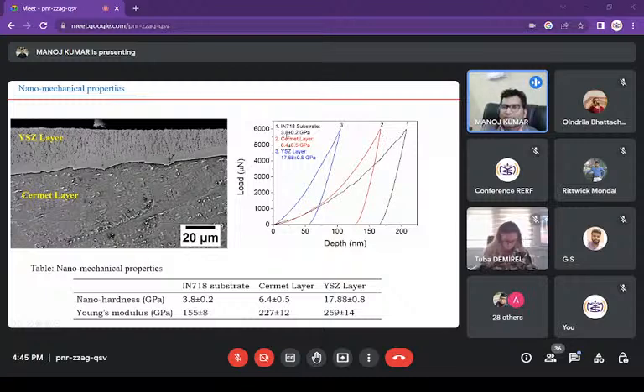So the substrate is having 3.8 GPa, the cermet layer has 6.4 GPa, and the YSZ top layer has almost 3 times of it, almost 18 GPa, which is characteristic of a pure YSZ layer. So this again reconfirms the existence of a thin continuous layer of YSZ.